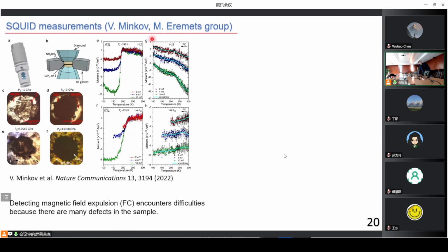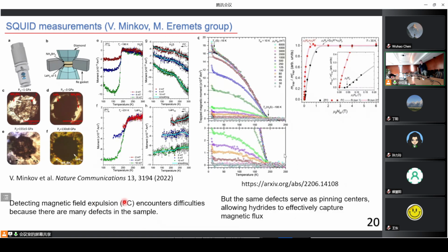And they didn't find the same response in field cooling, probably because such hydride samples have a lot of defects, and that's why the magnetic field just penetrates through the sample via such holes. Okay, but at the same time, these defects can serve as pinning centers and as memory centers. Actually, they can demonstrate the superconducting memory effect. And it was really proved by a group from Germany.